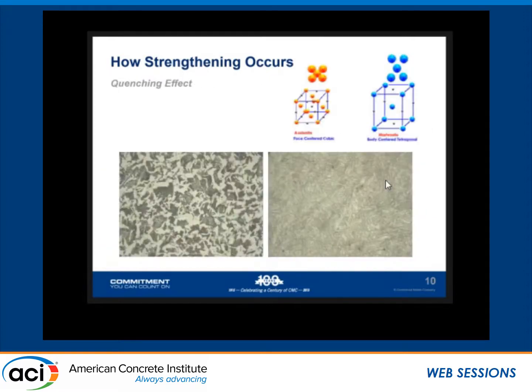Then you have a quenching effect. Now this is yet another microstructural change. When steel is hot, it's arranged in this type of a cube. When you quench it, you strain the cube and you trap carbon in there. So you get this kind of a rectangular shape. Really, if you look at the atomic bonds, it's more like two pyramids that are stacked point on point. So you go from this type of a microstructure to this type of a microstructure. Almost looks like a stack of needles.